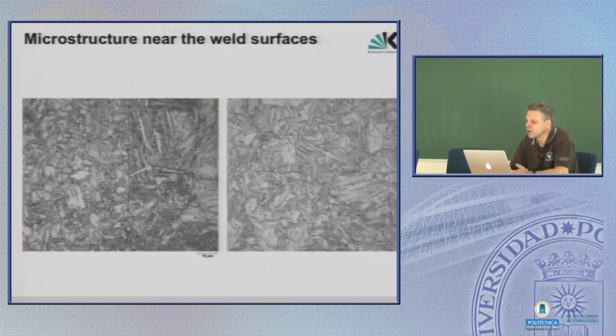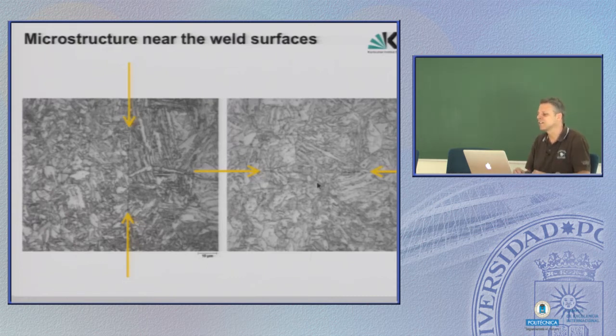And in this case you are right. This is a micro image of the weld line. I don't know whether you can still see any leftover of the weld line. Well, at least not from your distance. If you are very, very careful, you could imagine that at some parts there still was the end of one or other plate. But in principle, it looks perfect.